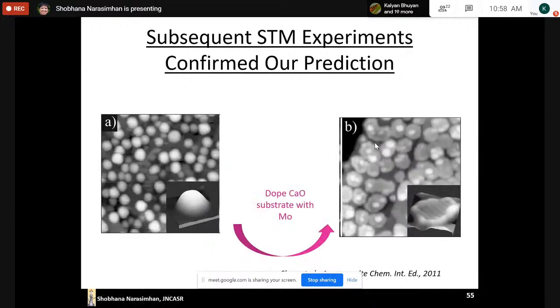And people in Germany, a group of Freund in Berlin, did this experiment. And they found, in these scanning tunneling microscopy experiments, that if you deposit the gold nanoparticles on an undoped substrate, they have a three-dimensional shape, whereas if you deposit them on a doped substrate, then the nanoparticles become flat. So this is a case where a prediction on how to design a material was made by density functional theory, and then people did the experiment and the prediction worked.